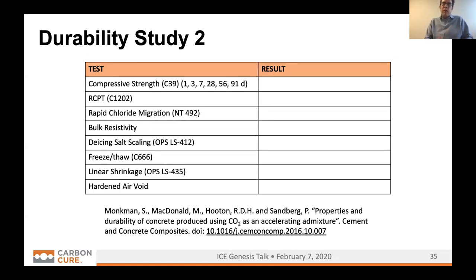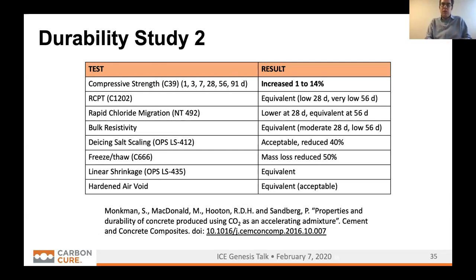We've repeated this study a few times. So in a separate study, we saw very similar results. We had maybe a bit of a bump on the strength. Everything else was equivalent, maybe a bit lower. Not enough to say we're necessarily improving the concrete durability in any great measure, but this process does not make the concrete any less durable.